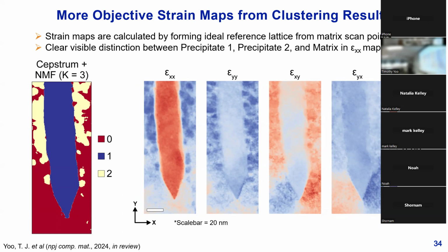And so what we do here instead is form these strain maps by taking a reference region of average lattice parameters from one cluster. We've just taken every point from, say, cluster 0 here, the matrix, to build our reference, and that's how we build the rest of these strain maps. And what we see here is that in certain points of especially this XX strain map, there are structural patterns that match up really nicely with our cluster map, particularly in these darker blue regions, where we know that the precipitate 2 lattice parameter in this direction is going to be shorter than that of the other two. And so it makes sense that those regions that are darkest blue here also match up with the yellow locations in the cluster map, and those in the lighter blue of the matrix, which is going to be in the middle between the precipitates in terms of lattice parameters in that direction, correspond to the red regions.